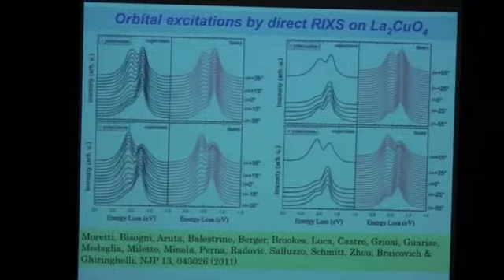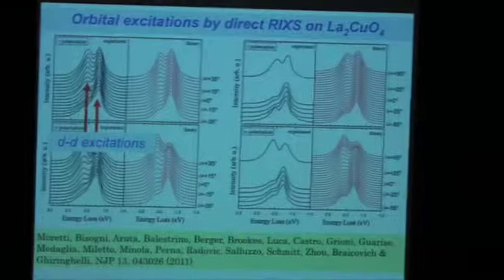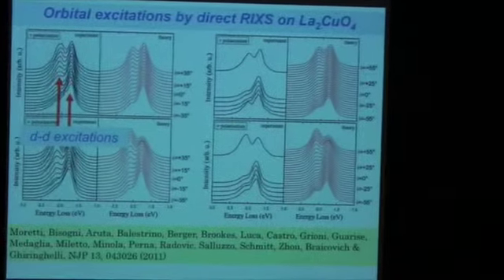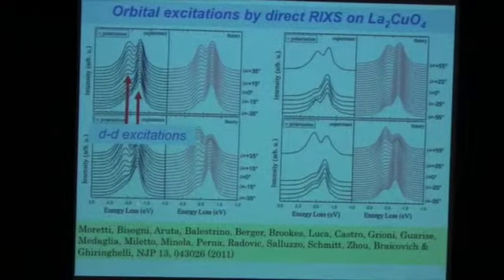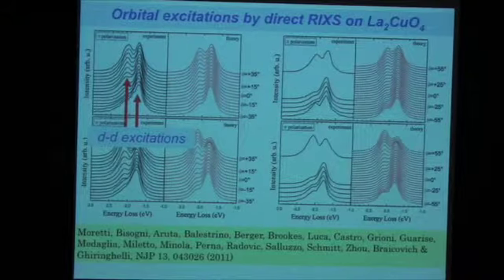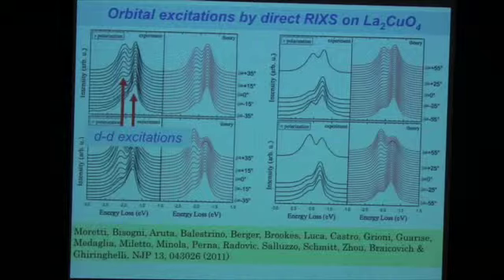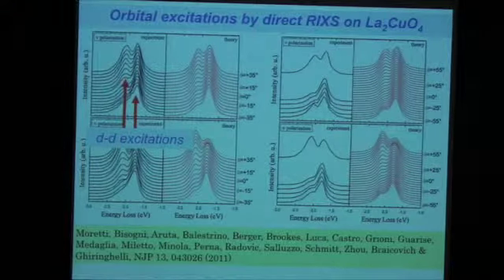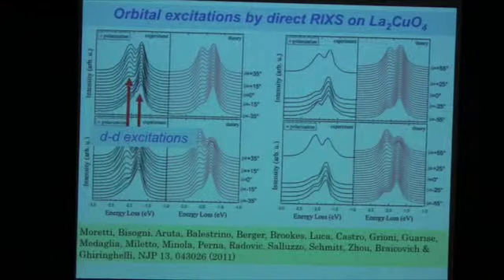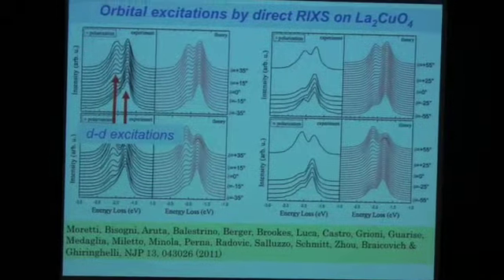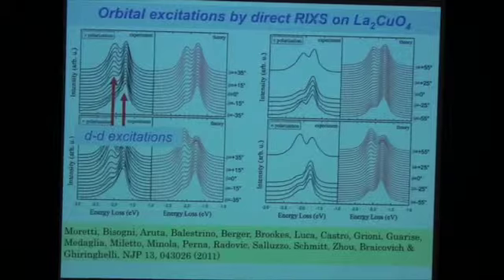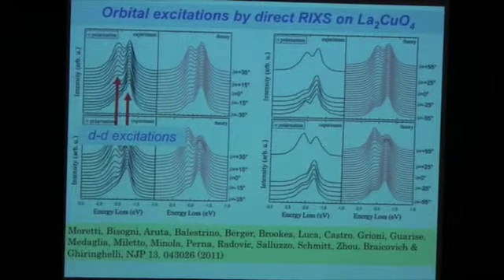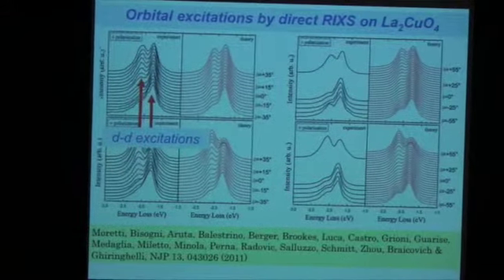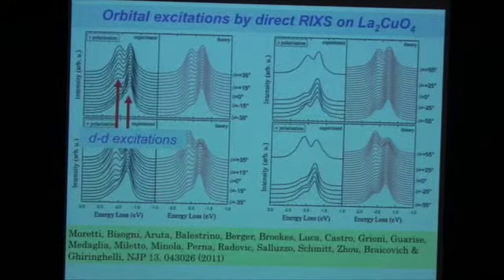So to your question, how large is that energy? Let's look at the data. So here you see the excitations. Actually, this is the EG, this is 3Z squared minus R squared, which is highest in energy. These are T2Gs. And it's about 1.7 eV to 2 eV, around 2 eV. And these data are represented as a function of angle of the incoming and outgoing photon, which translates into the polarization, or the dot product of the polarization of incoming and outgoing photon. And you see that the theory that I've represented in this rather naive triangle diagram works really very well. And the reason for that is actually it's all geometry. If I know my matrix elements, the rest is geometry, and that's the geometry of these orbitals, and that's what you pick up in the experiment.